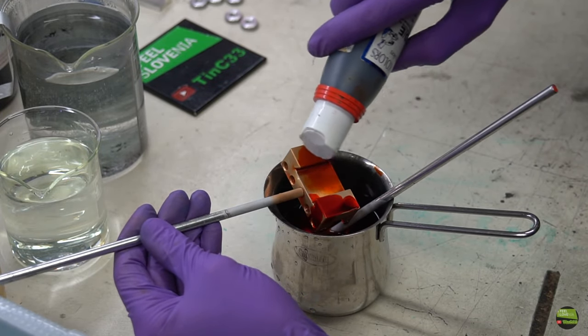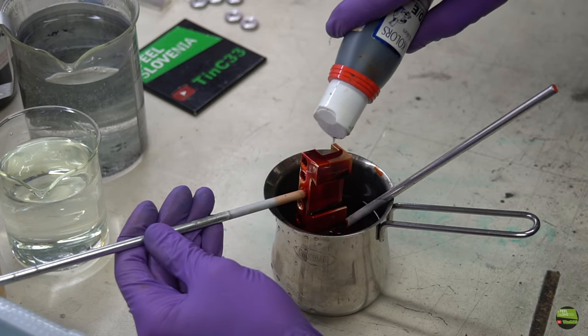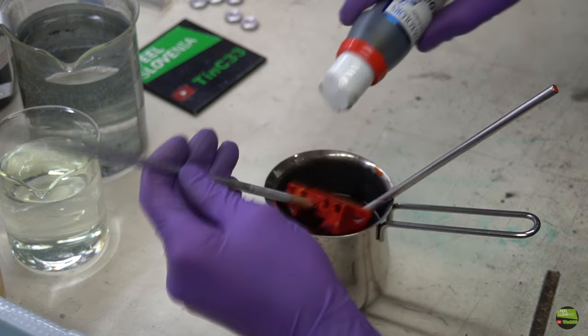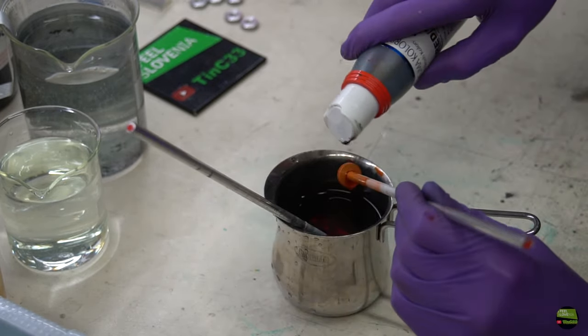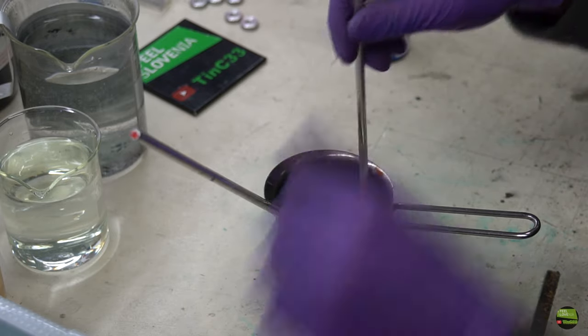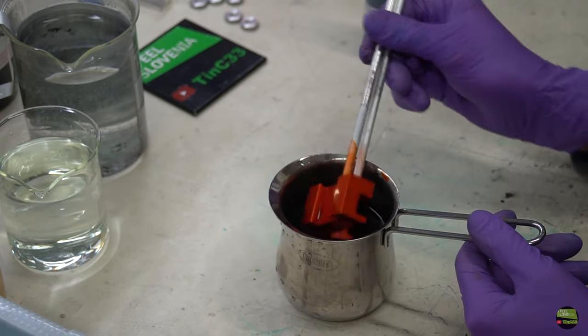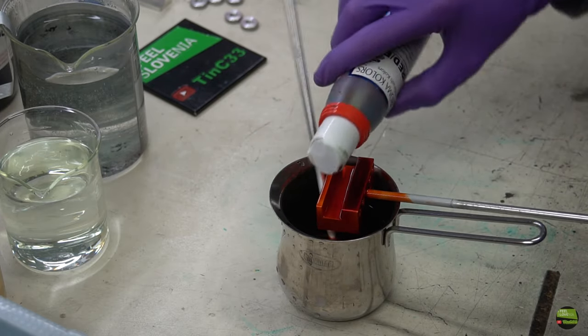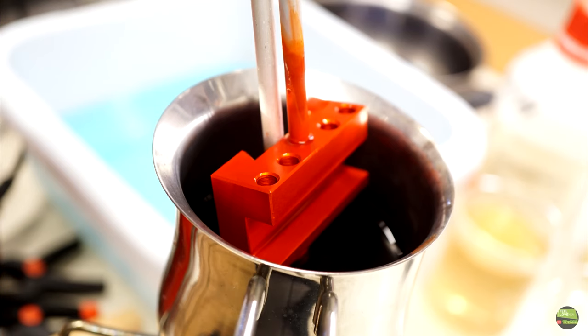But I like that liquid color because I can speed up that process by simply pouring a few drops of color directly onto the part, and so it becomes fully colored in a moment. After we get the wanted color, boil some fresh water and put the part in for a few minutes to boiling. Some color will disappear or it becomes a bit lighter, but that's normal.